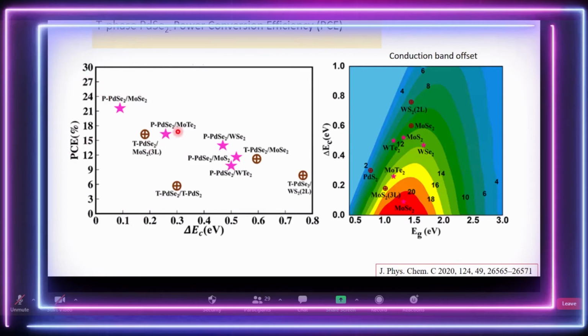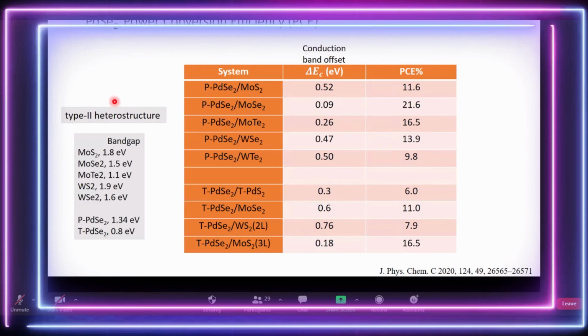So for all these cases, you can see the PdSe2, MoSe2, the pentagonal structure, or the tetragonal, hexagonal PdSe2 with MoS2, but with 3 layers, has a pretty good power efficiency, about 15 to 20%. So from there, you can again plot, this is sort of a table or a graph looking at the band gap structures. Then from there, you get the offset, and then you calculate the power conversion efficiency. And like I said earlier, this turns out to be pretty high, about 20% in some of the cases. In other cases it is very, very small.